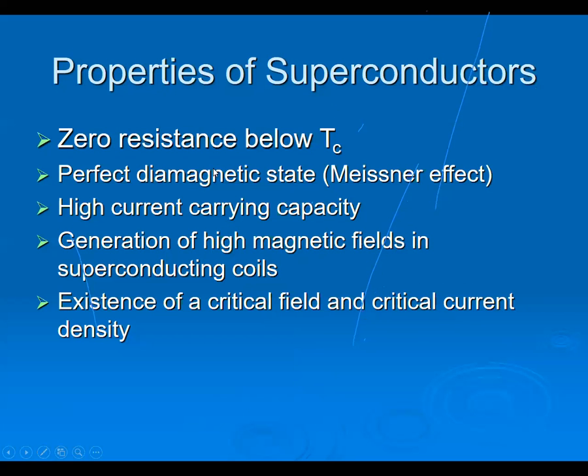Okay, the zero resistance. But a superconductor is not just a perfect conductor, it is also a perfect diamagnet. And that, as you all know, is what is called the Meissner effect. So when you have very near zero resistance, it will have a high current carrying capacity. If you carry high current, you can generate really high magnetic fields in the coils. But in addition to this, you have a critical temperature above which it goes to the normal state, but it is also limited by a critical field and a critical current density.